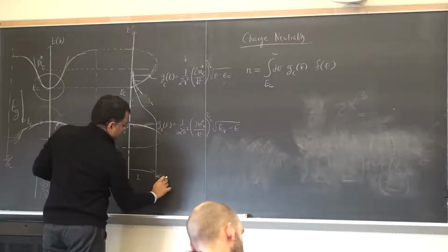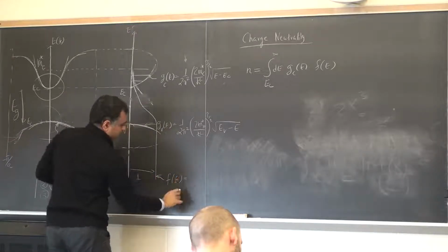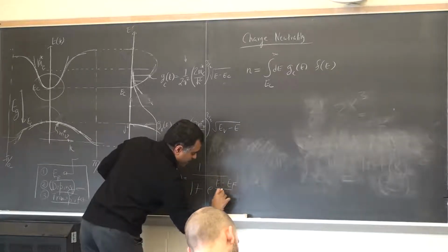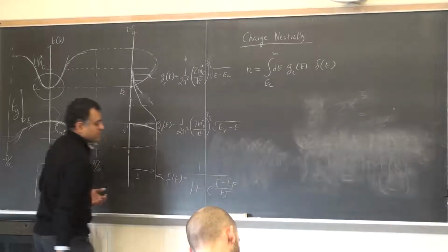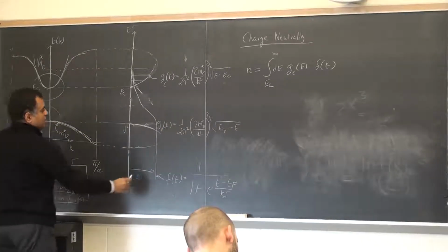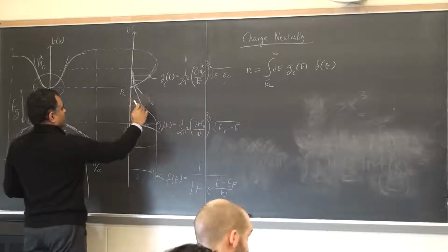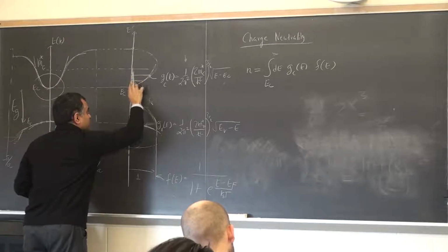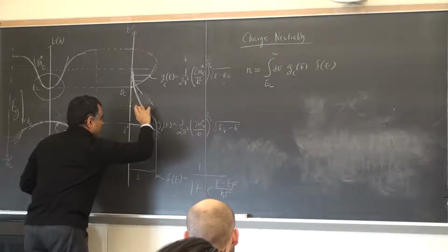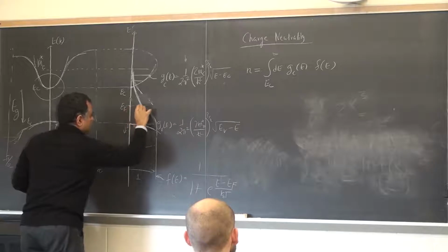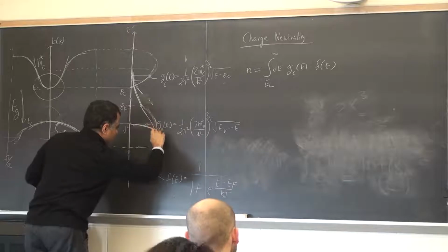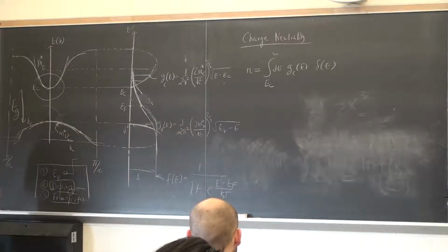And what I'm sketching here is the Fermi-Dirac distribution: one over one plus exponential of E minus EF over Boltzmann constant times temperature. So that's the Fermi-Dirac distribution. I'm going to just redraw it a little bit. Let's say there's a tail going down exponentially there, reaches half at EF, and then it's symmetric around, meaning the difference of it is symmetric around, so it kind of will go and do that. So that's how the Fermi function will look.